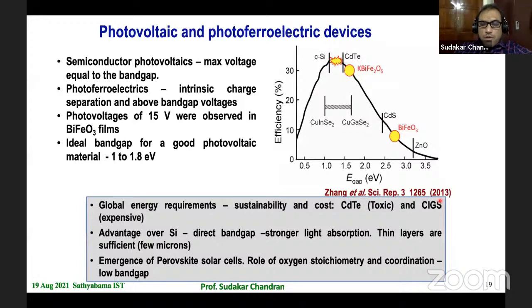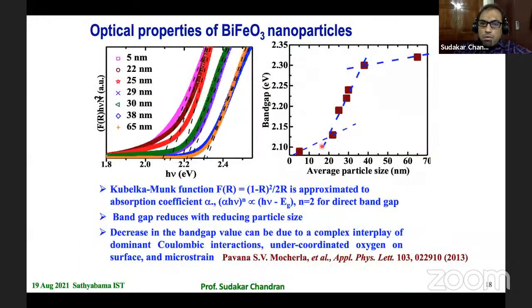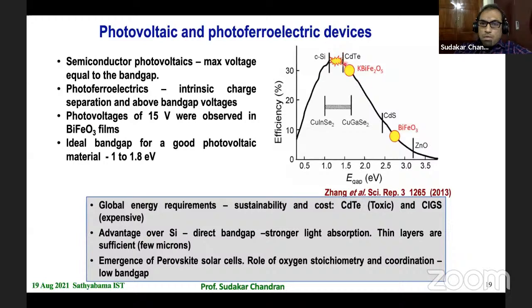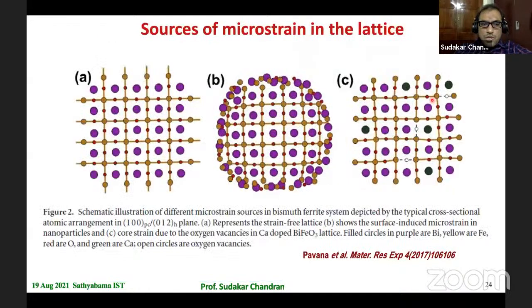But then what is the implication of controlling the band gap? For example, the bulk material of BiFeO3 has a band gap of around 2.78 electron volt. Now, by going to the smaller size, I'm able to decrease it further to close to 2, and maybe much closer to 1.5 eV, which is a typical band gap value of a material that is required for its efficient use as a solar cell material. Of course, silicon is the most commonly used solar cell material. There are cadmium telluride and many other materials being explored. But then we need stability, and energy conversion efficiency should be fantastic in the materials that we explore, and that's been the challenge.